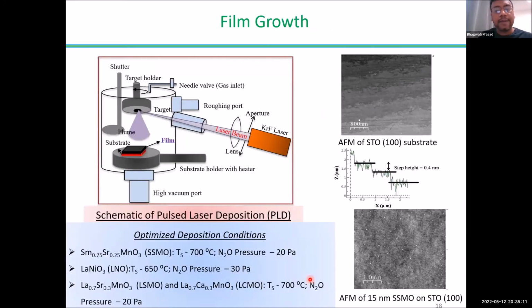Okay, so we grow the films by PLD, pulsed laser deposition. Most of you might know how PLD works. Basically you have a rotating target inside a vacuum chamber, then you ablate the target material with a focused laser beam, and if you have some background gas, you create a plasma plume that propagates and condenses on a heated substrate, and that's how you grow the films. Typically we use a single crystalline substrate. SrTiO3 is commonly used, and it typically has a step and terrace morphology. If the films you grow follow the same, that means you are growing good quality films, and you basically want to grow layer by layer, nice 2D growth.